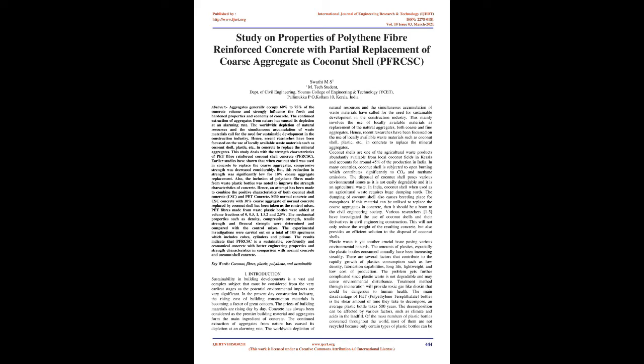M30 normal concrete and CSC concrete with 10% coarse aggregate of normal concrete replaced by coconut shell has been taken as the control mixes. PET fibers made from waste plastic bottles were added at volume fractions of 0, 0.5, 1, 1.5, 2 and 2.5%. The mechanical properties such as density, compressive strength, tensile strength, and flexural strength were determined and compared with the control mixes.